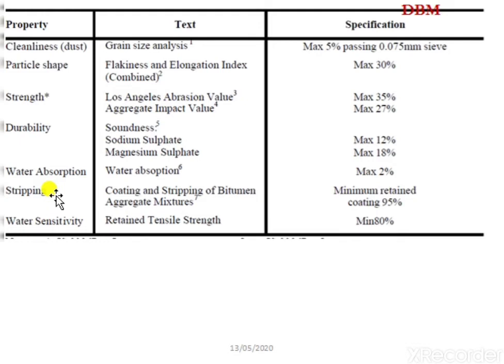And the stripping property. The test conducted to know the stripping property is the coating and stripping of bitumen aggregate mixture. This should have a minimum retained coating of 95%. Then the next property is water sensitivity. To determine this property, the test conducted is the retained tensile strength test, where the value should be a minimum of 80%. So these are the properties that the aggregate should possess, and these are the tests conducted to know the properties of an aggregate.